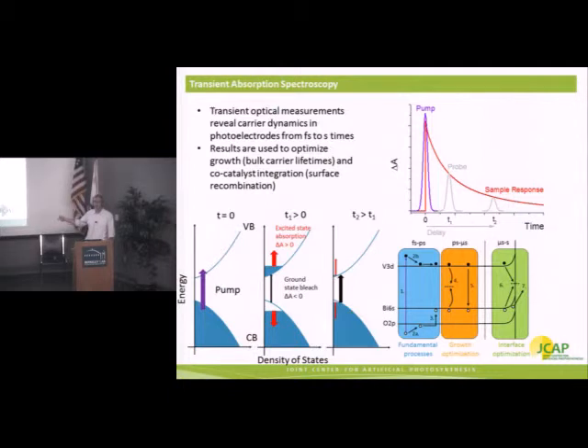So in the case of a semiconductor light absorber, those are typically those that are near the surface, because in this electric field, for example, in this N-type material, we have holes that have now accelerated to the surface. And these are exactly the holes that participate in the water oxidation reactions that we care about. So it's these holes that we ultimately want to determine their lifetimes, and specifically what they're doing, where they're going, and how we're losing them in terms of efficiency.